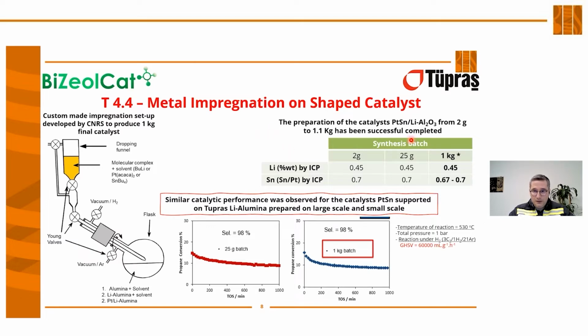When we look at the ICP results, we obtained very good results compared to laboratory and pilot scale production. Looking at reaction performance, we can say similar catalytic performance was observed for platinum tin catalyst supported on TÜPRAS lithium doped gamma alumina prepared at large scale and small scale under the same reaction conditions.